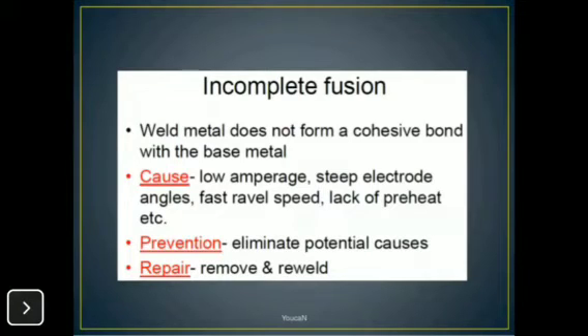This is the incomplete fusion: the lack of fusion between weld metal and base metal, and lack of fusion between multiple layers of the weld metal. These are the two reasons for attaining incomplete fusion. The cause is that the weld metal does not form a cohesive bond with the base metal. Causes are low amperage, steep electrode angles, fast travel speed, that is, the travel speed of the wire, and lack of preheat, etc. To prevent this, eliminate the potential causes.